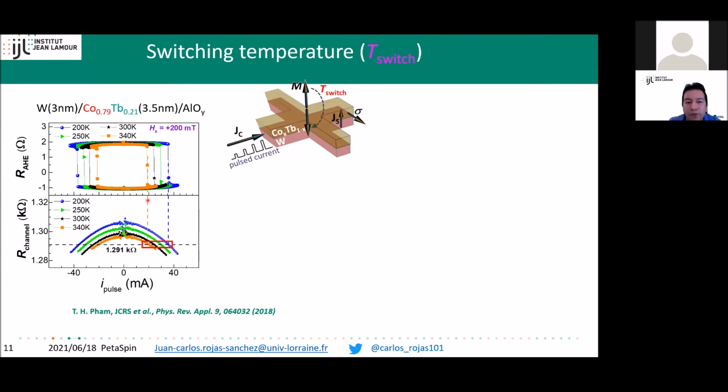And it's the same. So despite the cryostat or initial temperature in our experiment, the switching happens at the same longitudinal resistance. And a value of longitudinal resistance is a value of temperature. So having the same value of longitudinal resistance here means that we have the same temperature. That was very surprising for us, and it's a characteristic temperature that we call the switching temperature.